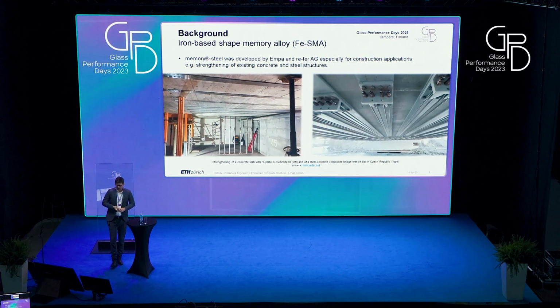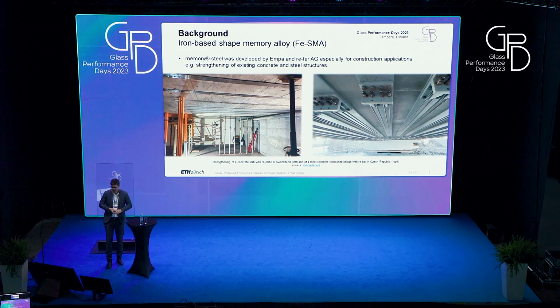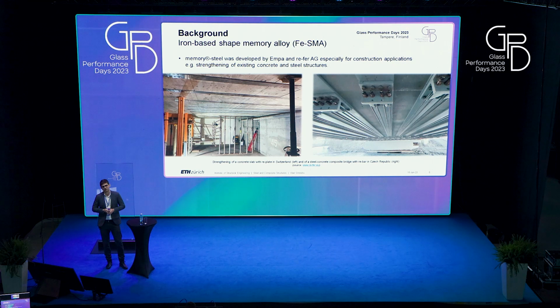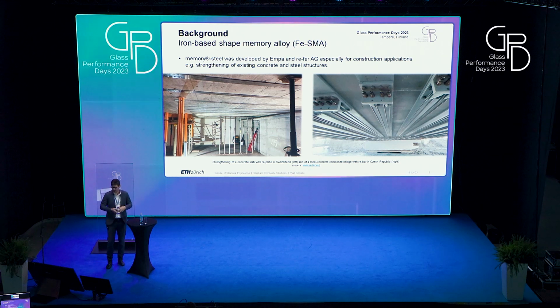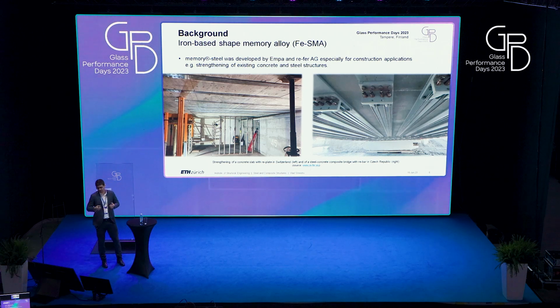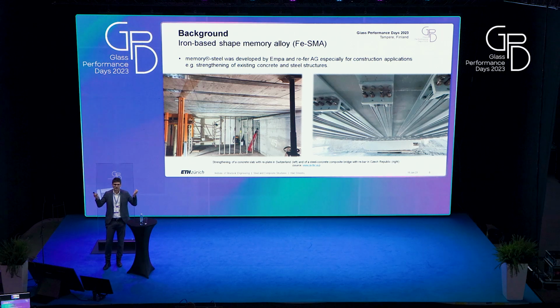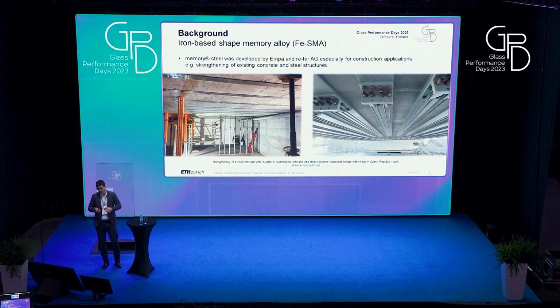In our studies, we used the product Memory Steel, which was developed by EMPA and Refer AG, especially for construction applications. In recent years, it was used mainly to strengthen existing concrete or steel structures, as you can see in these two examples. You have the predeformed strips or rods, you fix them mechanically to a parent structure, and afterwards, when you heat it, it would like to go back. However, it's fixed, so it will apply a pre-stress on the parent structure.